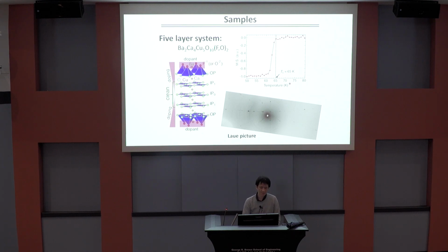The TC value is around 65 Kelvin, and the picture shows there is no buckling modulation, which is famous, for example, in bismuth compounds.